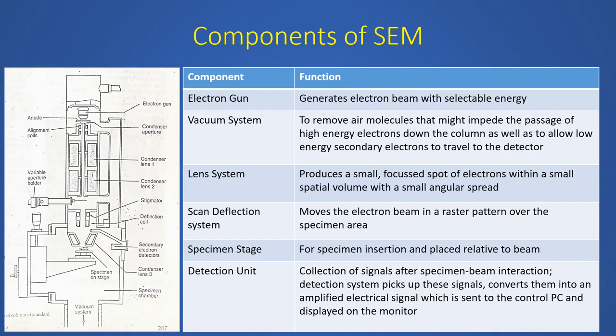Because as you go to higher and higher kVs, the electrons are much more energized. These are very highly energetic electrons and they'll penetrate the specimen. That is not something you want in an SEM. It's bad. So typically it is restricted to around 30 kilovolts. That's good enough, and you work at lower kVs for best results in biological SEMs, because we are only concerned with the surface features. We don't want signals coming from deep within the sample. We are concerned about the secondary electron signals. So that's why we don't have high kV SEMs, unlike TEMs.